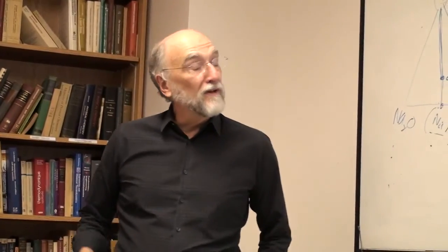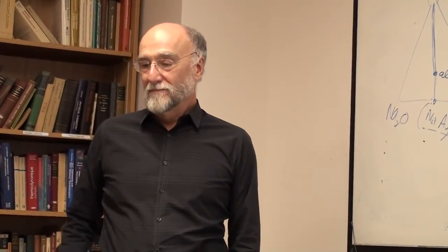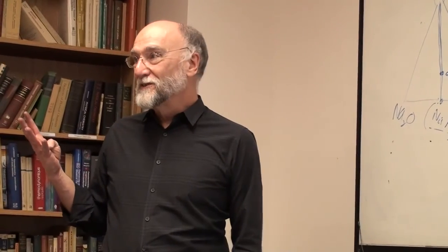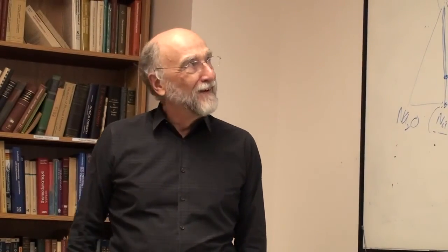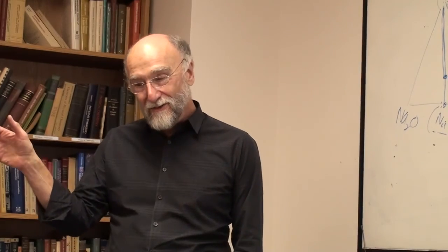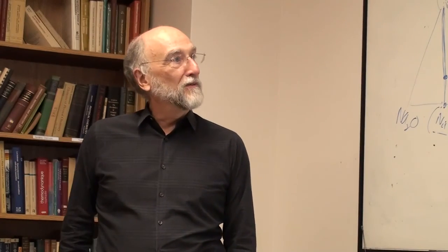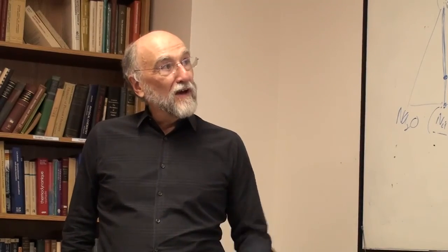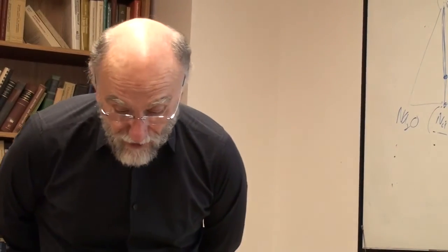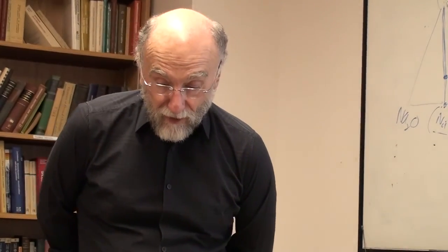Then there was the other one, the sulfide capacities. I already talked about that. If you dissolve sulfur as sulfide ions in these slags, you can use the modified quasi-chemical model in the, what do you call it, quadruplet approximation, putting oxygen and sulfur on one lattice and putting the silicon, whatever the alkalis, on the other lattice. If you want to look back at that, that's in file number 48.